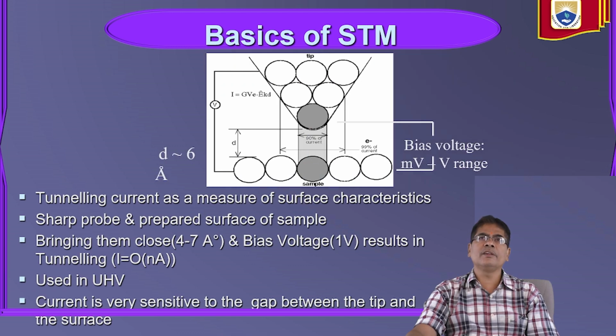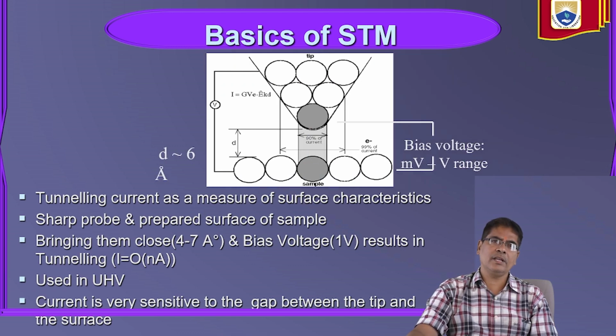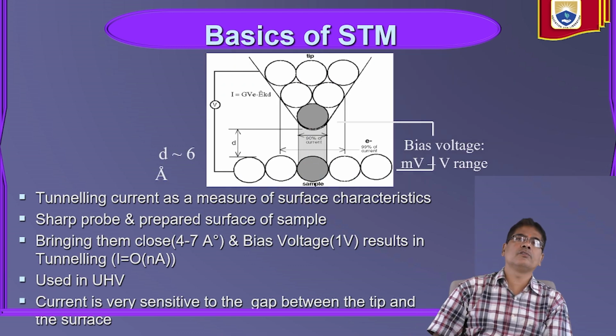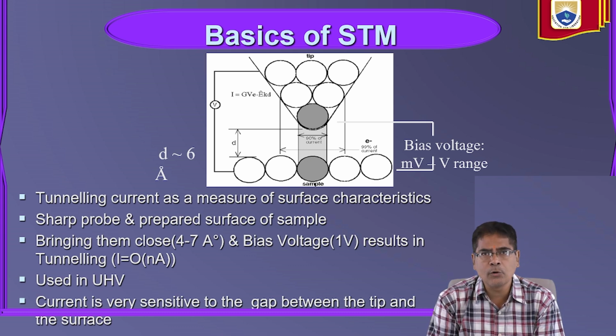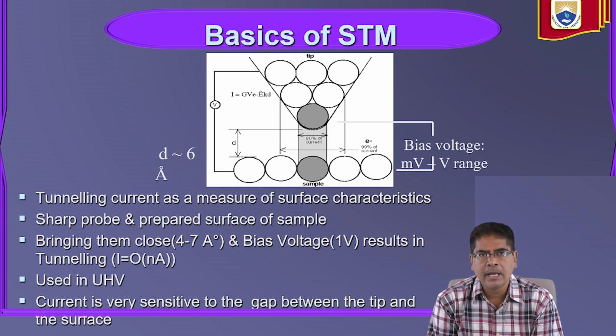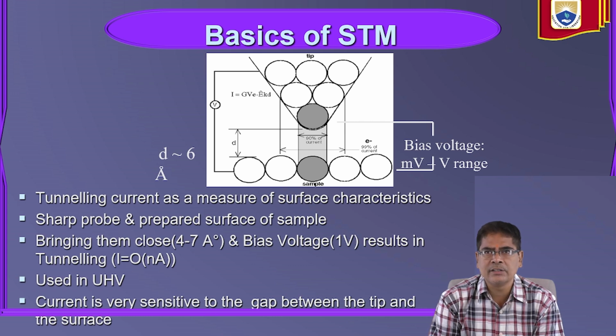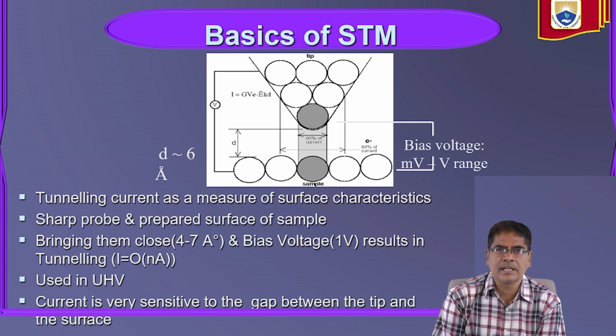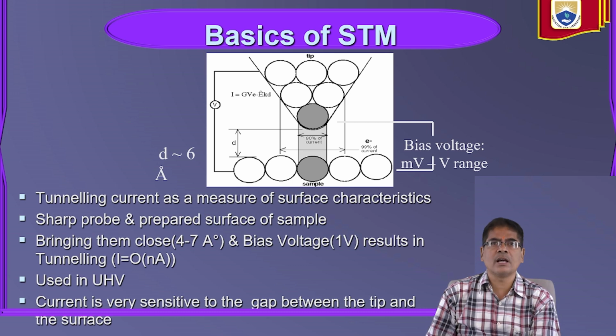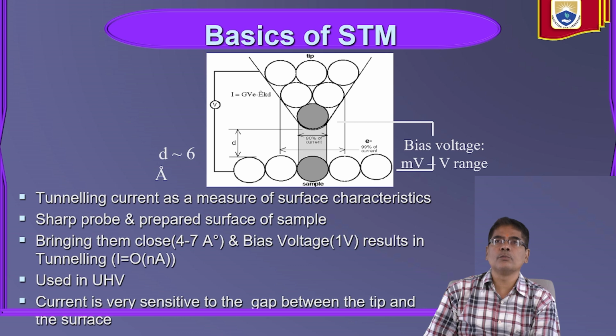So this is what the basics of STM is, right? The tunneling current is used as a measure of surface characteristics, using a sharp probe and a prepared sample surface, and bringing them close, around 4 to 7 angstroms. A bias voltage of around 1 volt results in the tunneling current, and this is done in ultra high vacuum. The current is very sensitive to the gap between the tip and the surface, right? So this is the bias voltage, and the distance is around 6 angstroms. The bias voltage ranges from millivolts to a volt.